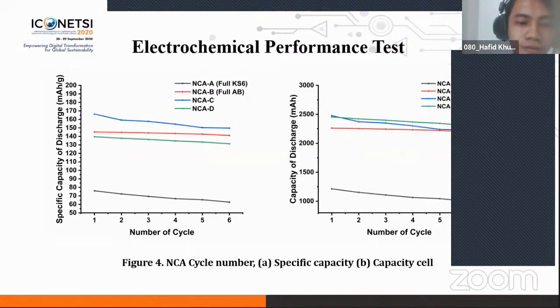Figure 4 presents the cycling performance of the NCA cell for 6 cycles using a 3000 milliampere current rate. Based on this result, it can be concluded that the high content of AB results in lower overall capacity, but higher cell capacity stability. Based on the characterization results, the surface area of AB is significantly higher than KS6, which has the electron transfer during charge discharge at a higher current. This can be the reason why NCA-A has a poor performance when charged and discharged at a higher current, 3000 milliampere.